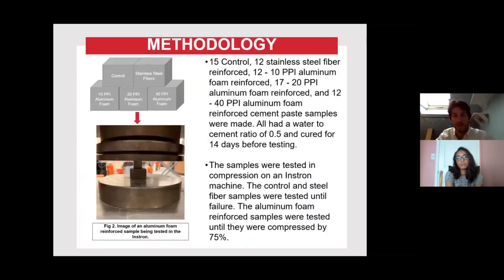To make this new composite material, we reinforced 1-inch cement paste cubes with stainless steel fibers and 10, 20, and 40 pores per inch aluminum foam. Control samples were also made for comparisons. All of these samples had a water to cement ratio of 50% and were cured for 14 days before being tested in compression on an Instron machine in WPI Structures Lab.